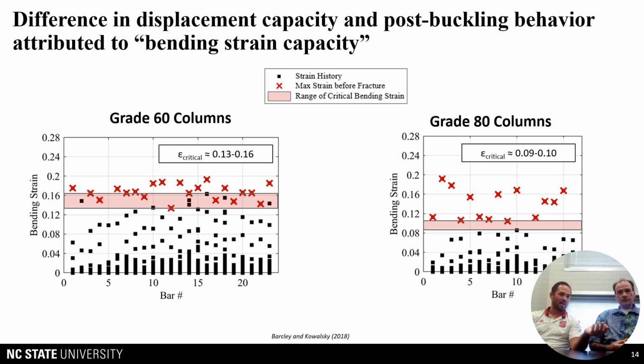But in the grade 80 columns, the bar begins to buckle, and when the bar first slightly buckles is when you start to be able to measure bending strain. For the rest of the test, the bar is straight, so you assume there's no bending strain at all. But we saw in these grade 80 bars that when they buckled once, came back, they were fracturing the cycle after at a much lower bending strain. So the X on the first column is around 12%, and then there were some other ones that we continued to look at. Between 9, 10, maybe up to 11, they would be subjected to that bending strain, and on the next cycle they would fracture.